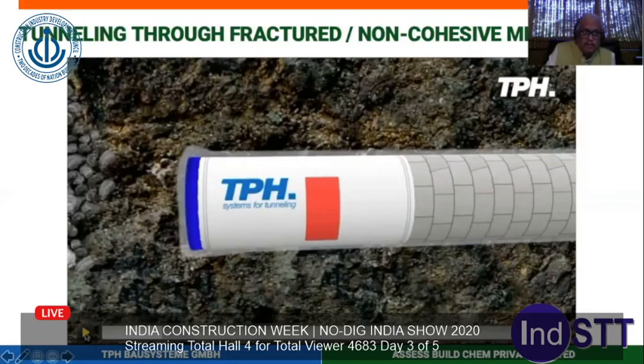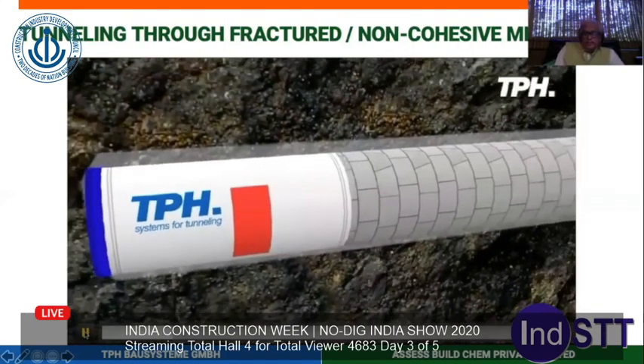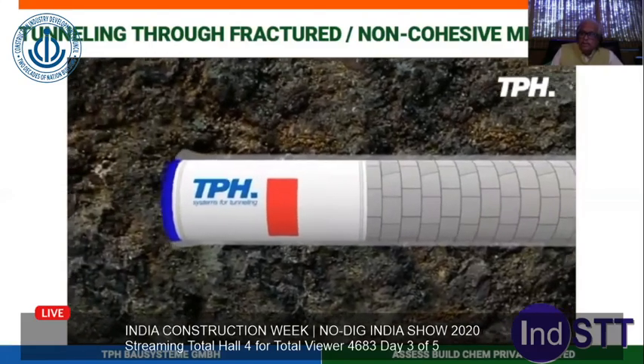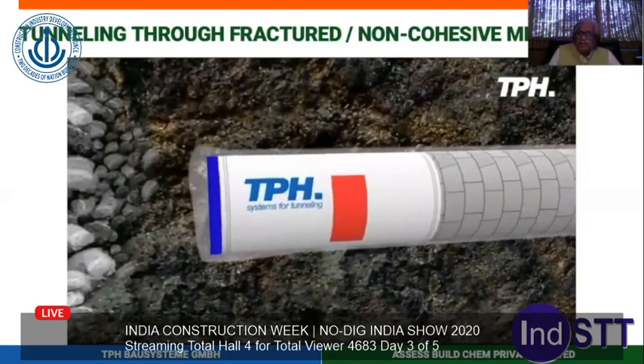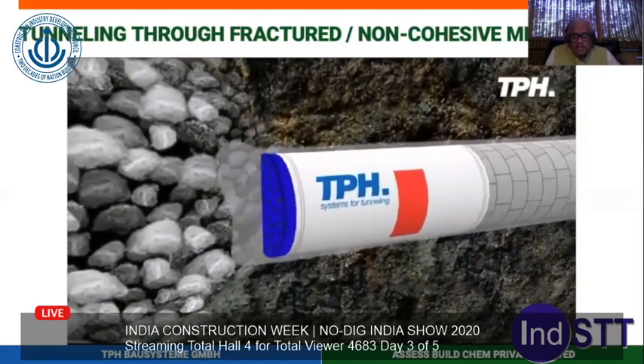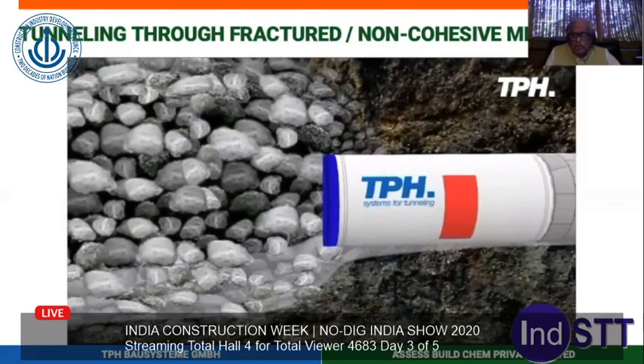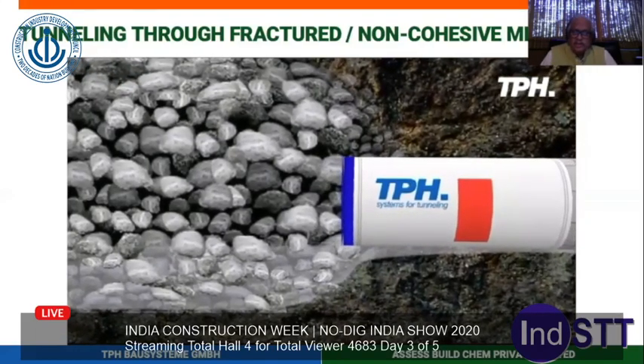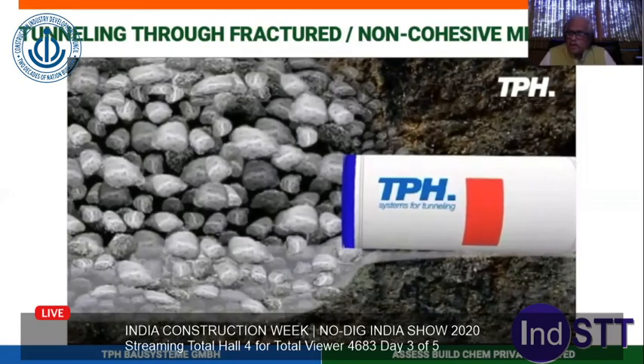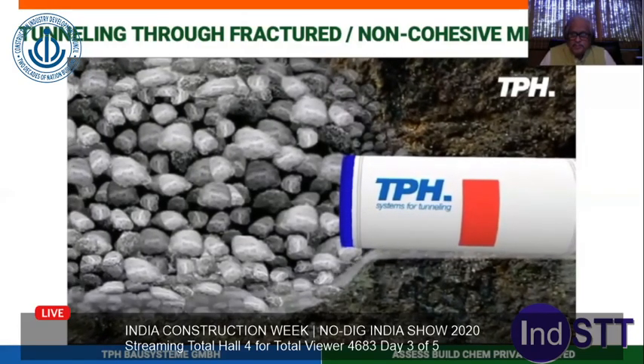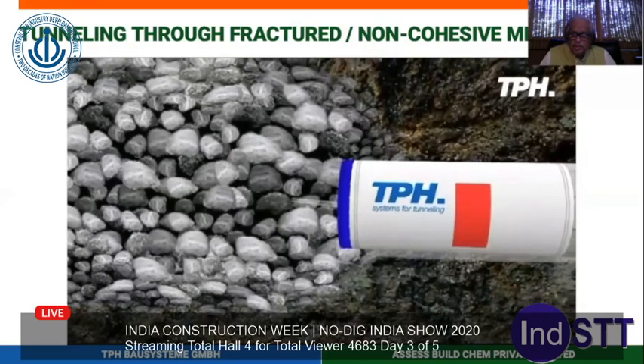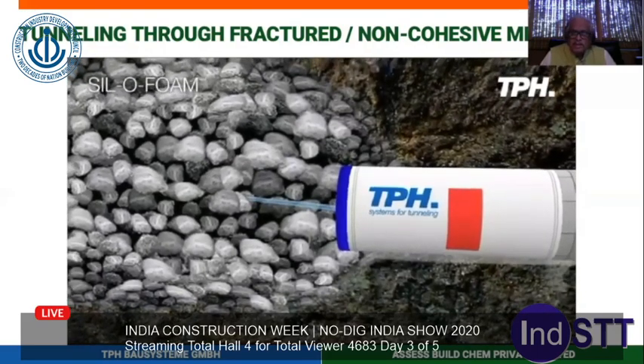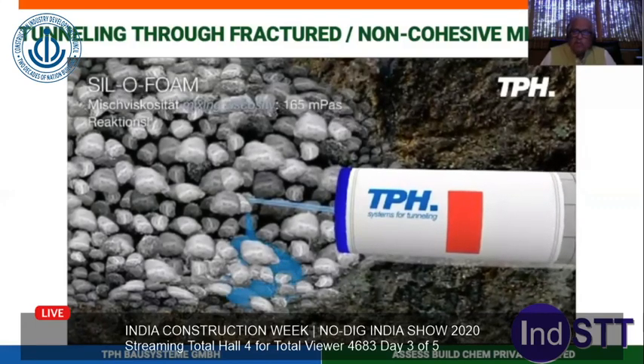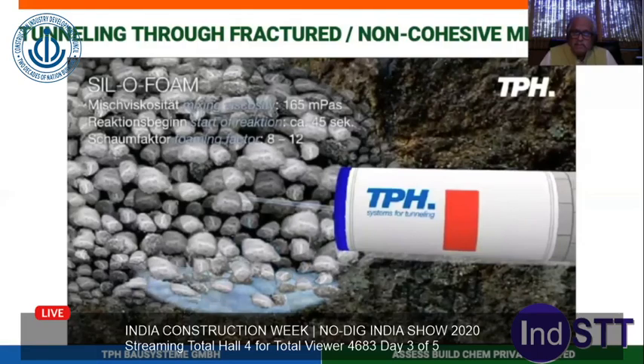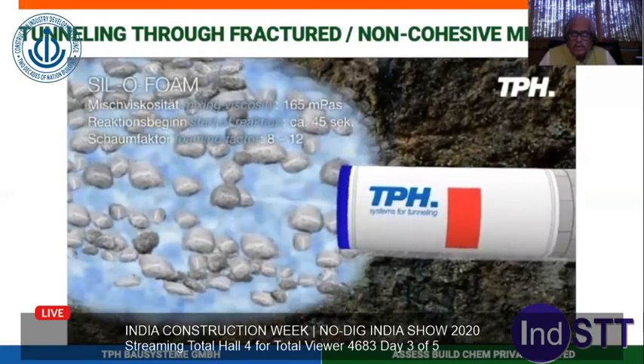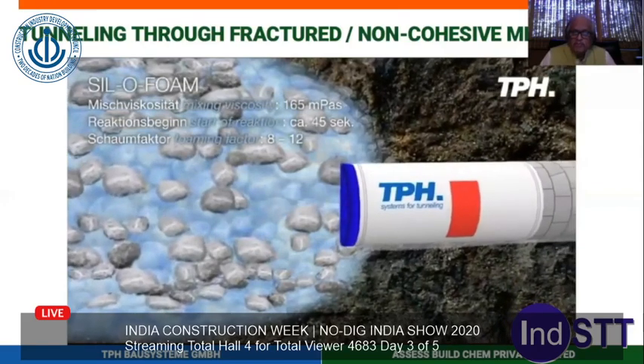a tunnel boring machine. When the tunnel boring machine is moving around, geotechnical surveys have already identified that at X meters you are having this. So you are already putting in the silicate foam. It cannot move. The shield cannot move. So the silicate foam is injected. This foam is not injecting 50 or 60 times. Within 45 seconds, they have maintained the foaming factor at 8 to 12.